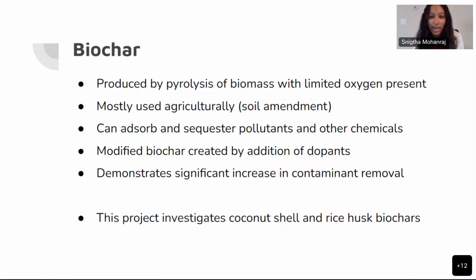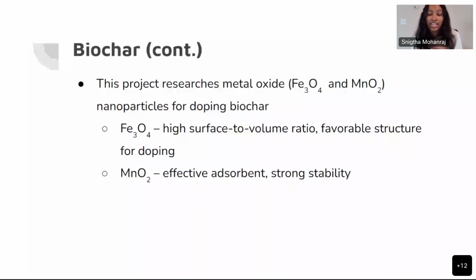I can modify this biochar by adding dopants, which can demonstrate a significant increase in contaminant removal because of the enhancement of the biochar's properties. So my project investigates coconut shell and rice husk biochars to see how the material affects it, and then two different dopants, which are iron oxide and manganese dioxide nanoparticles. The iron oxide has a high surface to volume ratio, meaning that there's more area available to attract and sequester the pollutants, and then there's a favorable structure for doping.